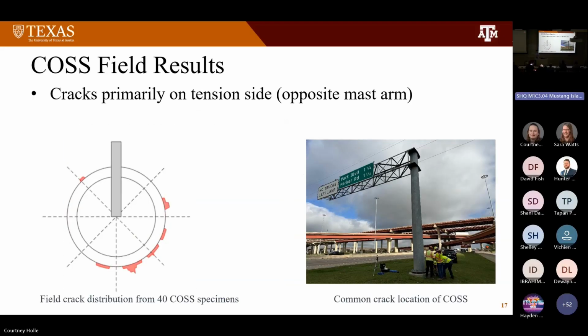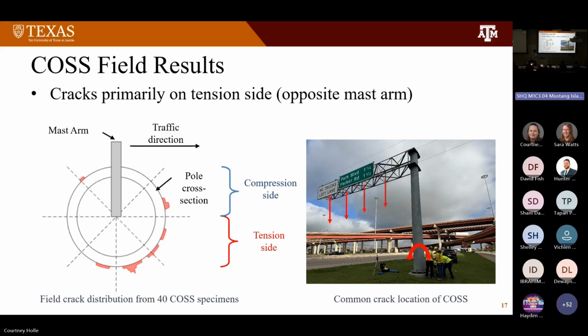So here is the result of the field assessment from 40 COSS specimens. We normalized the layout of the pole, including mast arm orientations and traffic direction. And because of the mast arm, the opposite side of the mast arm has a tension stress. And the red marks on the diagram indicate the crack locations. So here what we can see is cracks are primarily located on the tension side, which means the weld toe on the opposite side of the mast arm is the critical weak area.